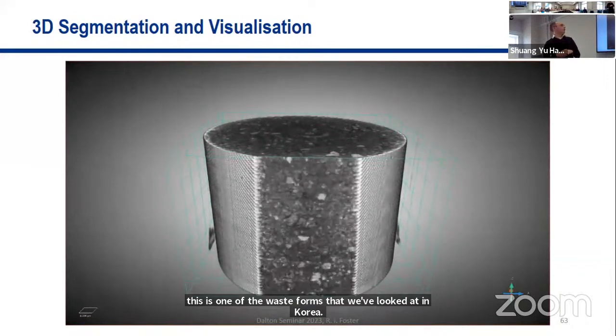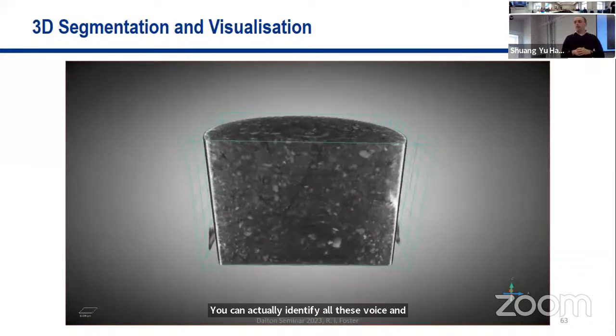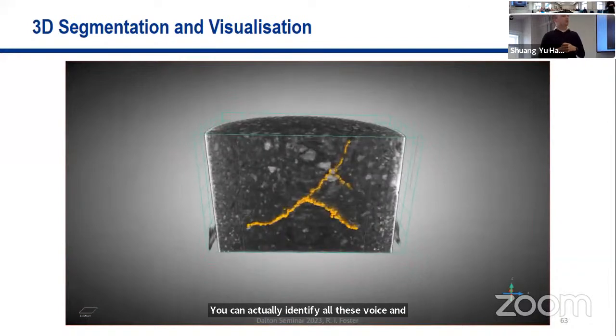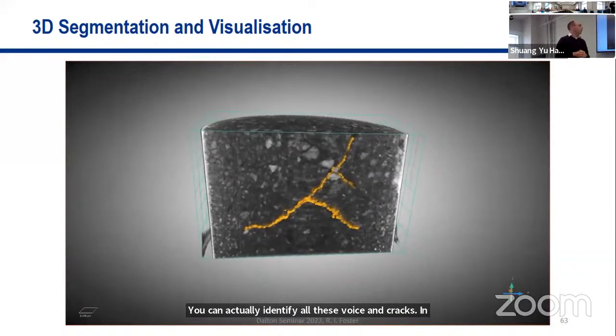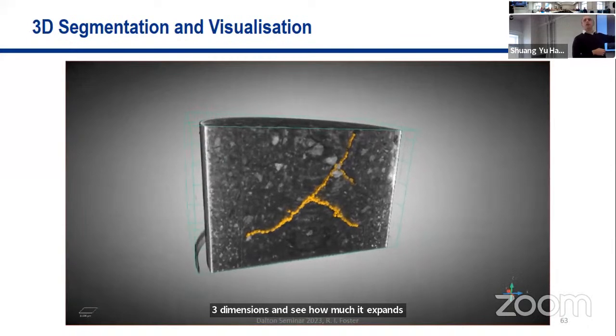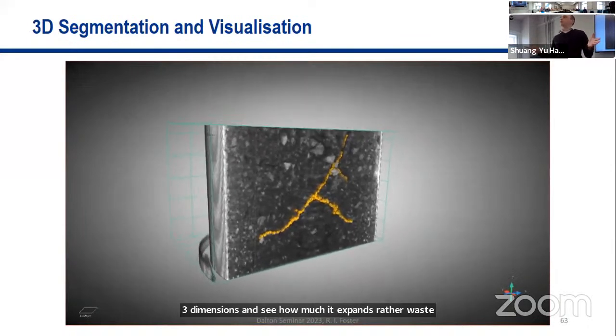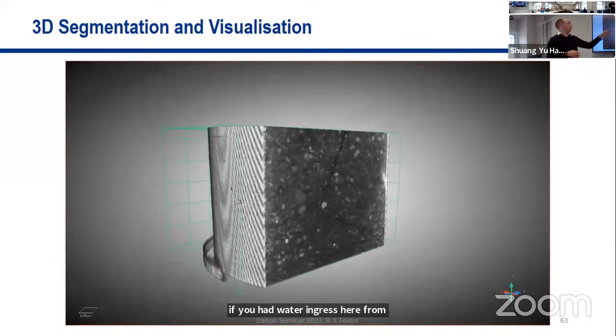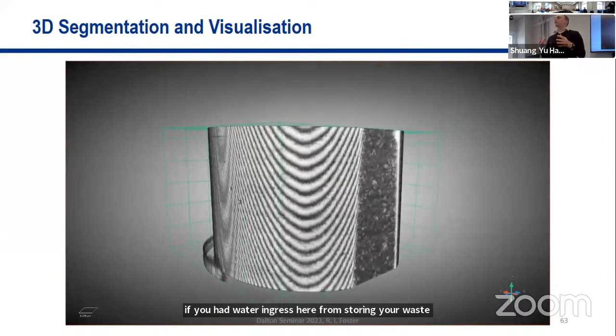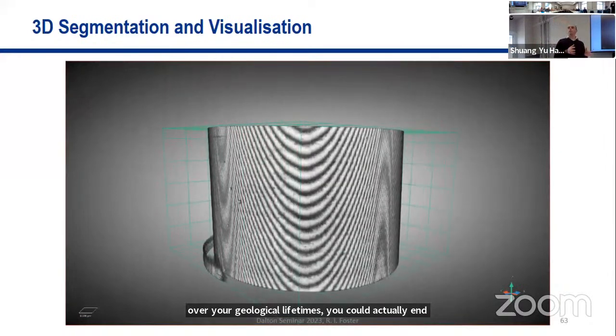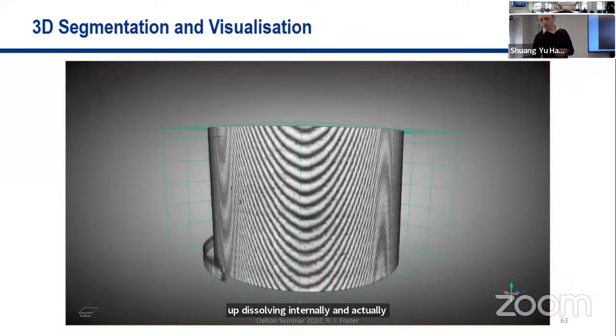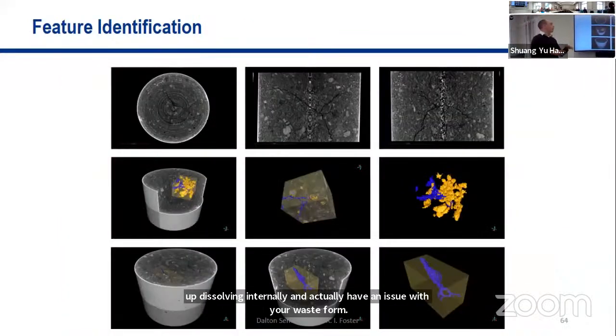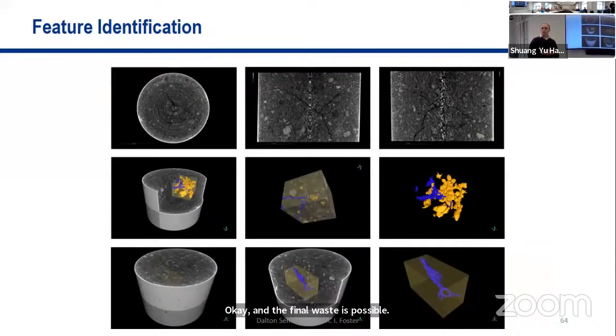You can actually identify all these voids and cracks in 3 dimensions and see how much it expands throughout the waste. So if you had water ingress here from storing your waste over your geological lifetimes, you could actually end up with dissolving internally and actually have an issue with your waste form and final waste disposal. So here's just one of the data sets that I worked up very briefly, where we can actually identify the cracks, porosity, and things like that.